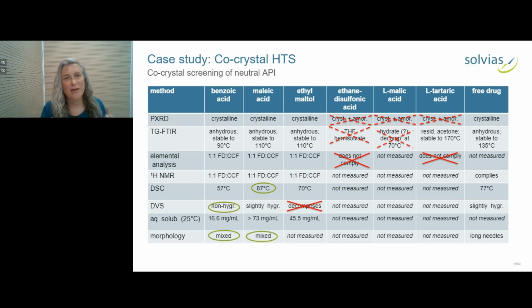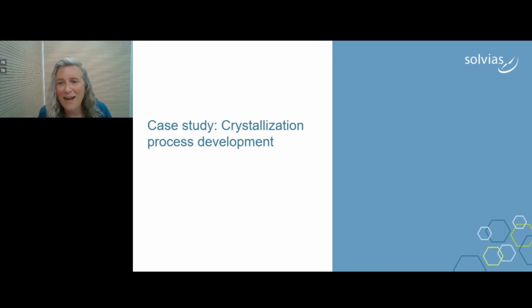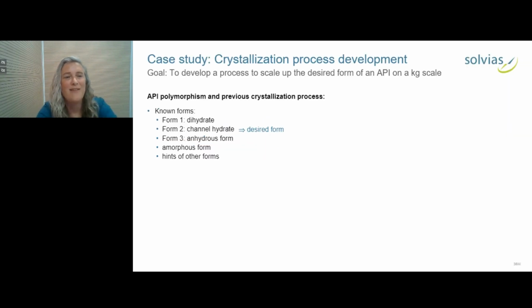And in the end, both the benzoic acid and the maleic acid had mixed morphologies. So they didn't only have those long needles anymore, but there was a chance to really create a more equant morphology. And so in the end, this screening gave the customer the choice of 2 co-crystals with superior properties to the free drug. The final case study that I will present is related to crystallization process development.